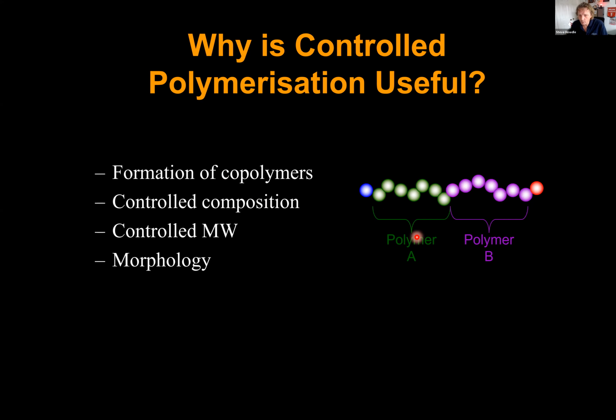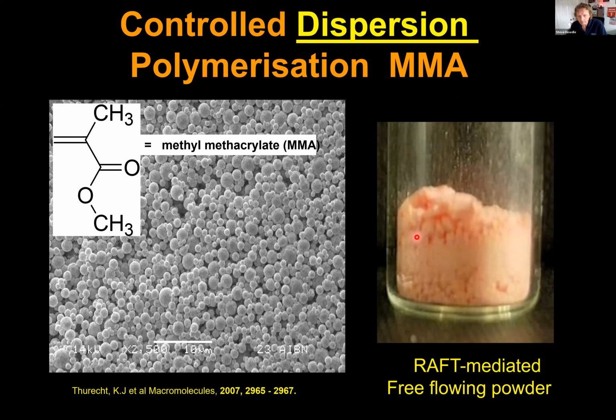We looked at using RAFT controlled polymerization, and we showed that we could get very nicely controlled particles of PMMA, polymethyl methacrylate, and the RAFT agent we were using worked very effectively to control the molecular weight. Also when we looked at the sample afterwards, you could tell the RAFT agent had worked because the sample has a yellow tinge, or in this case, a pink tinge, that shows the RAFT agent is present. This showed us we could use RAFT agents to build up molecular weight, to control molecular weight, and to allow us to make block copolymers.